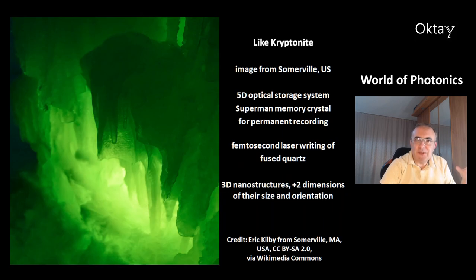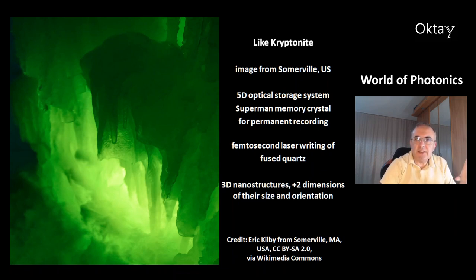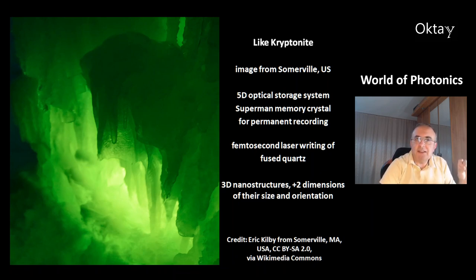This picture looks like kryptonite from the movie Superman, but this is an image from Somerville, USA. You can make 5D optical storage systems — also called supermemory crystals — for permanent recording. A femtosecond laser is used for writing into fused quartz, producing 3D nanostructures plus two additional dimensions that come from the size and orientation of the nanostructures.